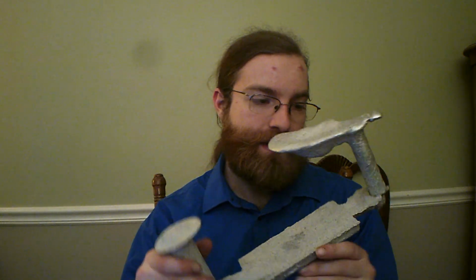I also wound up using a larger riser. That probably helped with some of the voids, but more than anything else, I rammed a lot harder, and I also moistened the sand a bit so it was a lot wetter. Now, I still wound up with a little bit of sand stuck in the first C of the pattern when I pulled the thing out. And that happened twice.